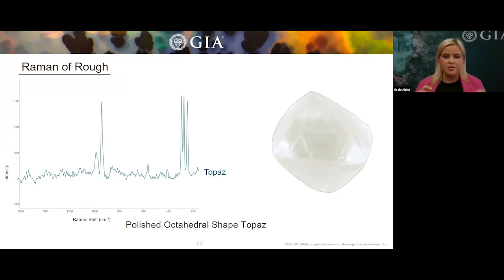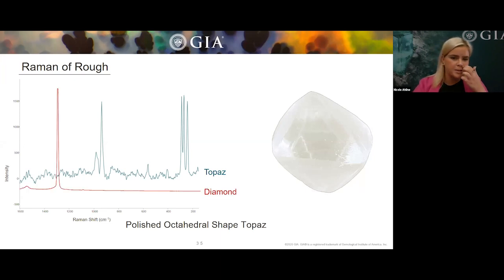So this stone received a Raman spectrum due to the rough surface interfering with getting a clean refractive index. And it has a spectrum for topaz, but it was polished and carved to imitate a diamond. And so a diamond has an SG of 3.52, and topaz has a very similar SG of about 3.5 to 3.6. So the SG wasn't useful in determining the identification of this stone, but this spectrum was. And let me show you, this is the Raman of a diamond, so very different. So with using that Raman, the stone presumably being double refractive, and also inclusions present in the stone, was the evidence that this gemologist needed to correctly identify the stone as a topaz.